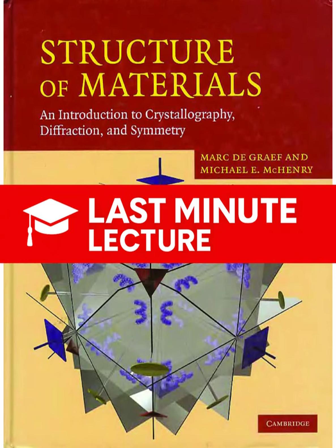The structure factor, F_HKL squared, provides the foundational intrinsic scattering power. That's determined by where the atoms are and what they are. And then that intrinsic ideal value is scaled by all the geometric and experimental factors. The Lorentz-polarization factor and the multiplicity factor boost the intensity based on the geometry of the experiment and the crystal, while the Debye-Waller factor and the absorption factor both reduce the intensity based on thermal motion and how much the sample eats the beam. That's the whole picture.